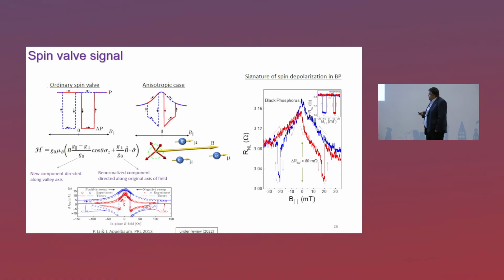Basically, both in germanium and in black phosphorus, we have the g-factor anisotropy, meaning that even though you are applying the fields only in the in-plane direction, the spins are also feeling an effectively different direction of the magnetic fields. Therefore, you start to have some kind of relaxation near the zero field.